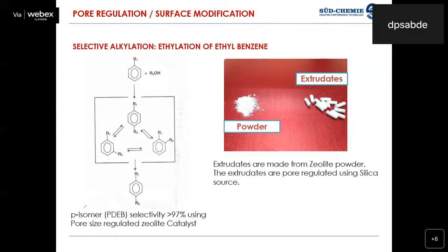So this is one technology which is developed by IPCL. Now it is with Reliance. So this is basically a catalyst for PDEB, paradiethyl benzene application, where the selectivity of more than 97% for the para isomer is achieved. And this is done by pore regulation of the zeolite catalyst. If you look at the right side, the zeolite powder is formed into an extrudate. And this extrudate basically is pore regulated by using some kind of a silica source.